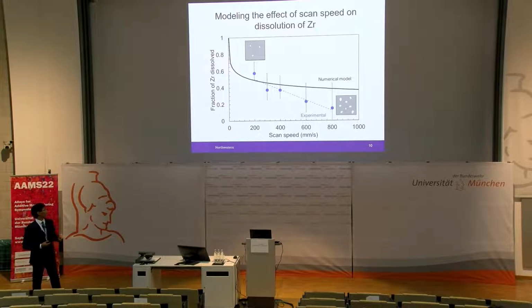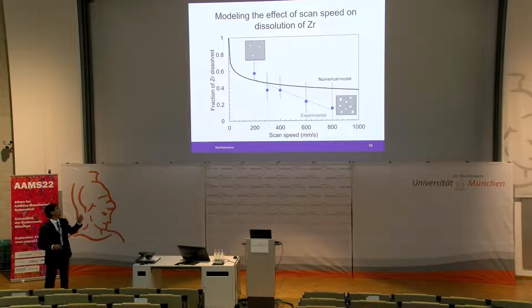So let's do this now. Let's represent the effect of scan speed. Again, what we see from the model is that it reproduces qualitatively our experimental observations, in that as the scan speed decreases, the amount of zirconium dissolved increases. You can see that the agreement between the numerical model and the experiment is okay, but the main point is that we're reproducing qualitatively our assumptions.